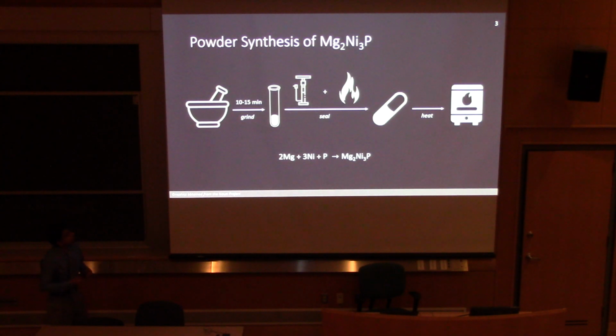So for the powder synthesis, we first take a stoichiometric, or 2:3:1, ratio of magnesium to nickel to phosphorus. We grind it for 10-15 minutes in a mortar and pestle. Once we've ground it, we put it in a quartz ampule, after which we vacuum purge it to prevent any sort of gaseous media in our tube, because in the subsequent step, in which we heat it, the gaseous buildup will cause the tube to explode. So you don't want any sort of gaseous media in your tube. Then we flame seal it such that the tip is closed off and it more or less looks like an elongated pill. And then we subject it to a heating cycle.